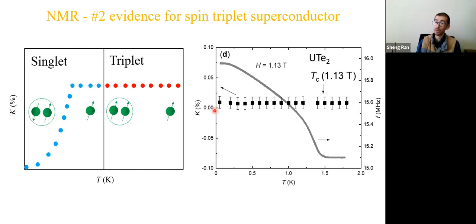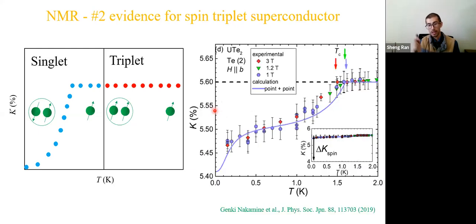But of course, this was done on powder, and many things were not clear. For example, the Knight shift is supposed to have a spin susceptibility and an orbital contribution. So later on, a Japanese group did a more careful study on single crystal samples. They ruled out the orbital contribution. The orbital contribution is supposed to increase with magnetic field. They measured the Knight shift at 1 Tesla and 3 Tesla. They do not see significant change. Therefore, they think the orbital contribution here is very tiny and negligible.